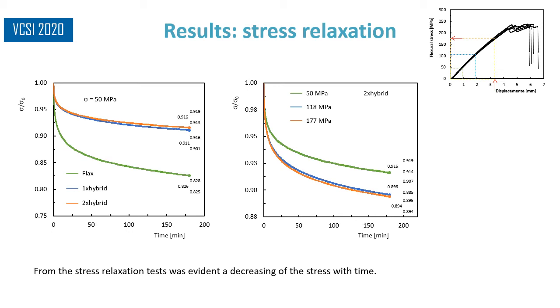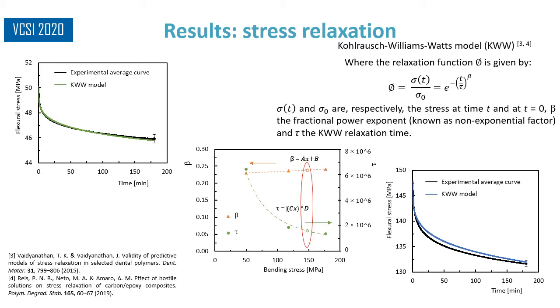From these tests, the stress was plotted versus time and the figure presents the results in terms of average curves. To predict the viscoelastic response, several models are presented in the bibliography. One of them, widely used in various studies, is based on the KWW model. The KWW model was applied to predict the behavior in a displacement. Step 1, application of the model. Step 2, estimating the model parameters. And finally, application again of the model and comparison with the average curve.